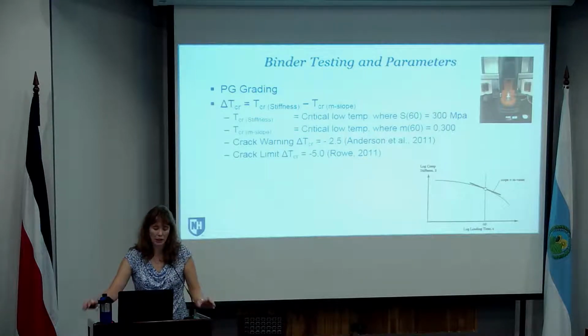Okay, but it's really looking at this parameter, looking at the stiffness versus the relaxation capacity. And as that delta TCR becomes more negative, really what that's indicating is you're losing the relaxation capacity, which means you're more prone to cracking.